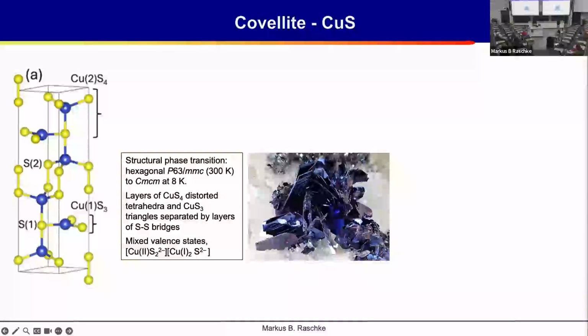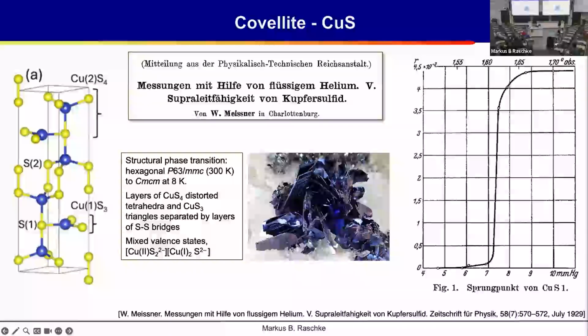And it actually turns out that because sulfur is now the complex ingredient, we have different oxidation states. This is because the sulfur can also pair and then have a negative charge. And so we have copper 1+, and then we have copper 2+ on these different lattice sites. And this actually becomes a superconductor, and this was already noticed by Meissner, after whom the Meissner effect and the magnetic field phenomena were named, and it has a transition temperature